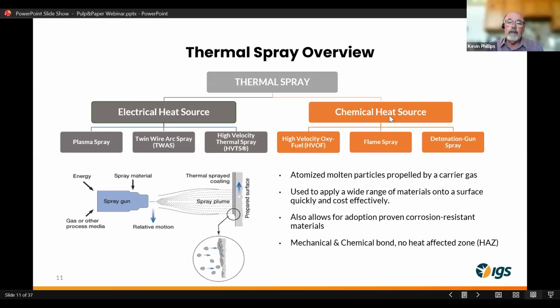Metals in the chemical heat source family, HVOF, which is a high velocity oxy fuel, it produces a fairly dense coating, but it has a lot of residual stresses just due to the nature of how it is applied and the heat that's involved to generate that cladding for your particular assets. Flame spray or detonation, that's usually going to be found more so in a shop applied application, but again, they still also have the effects of a very heat stressed final cladding.